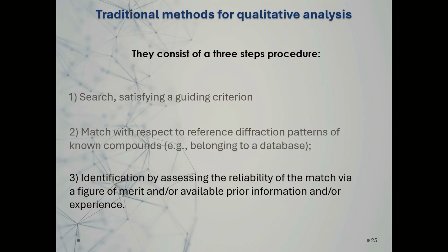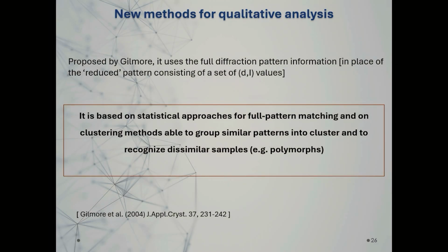And in the end, we have to assess the identification and try to assess the reliability that is given via a figure of merit. So assessing a phase is a combination of the experience of the researcher performing the qualitative phase analysis and the already known information about the sample. For example, I know that it's an inorganic sample, so I have to exclude what is organic, for example. And then, of course, I have to give the right importance to the figure of merit, that is a measure of whether that phase is inside the sample that I'm analyzing.